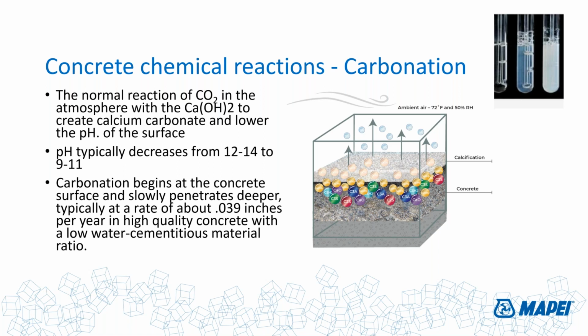So that's helpful for us as floor covering installers, to allow a concrete slab to carbonate, and there is a considerable difference in solubility in water. Calcium carbonate is not that soluble in water. Calcium hydroxide is extremely soluble in water. I would rather be working on something that is not soluble when I'm putting water-based adhesive on top of it, rather than something that is extremely soluble. That carbonation process typically will decrease the pH of a concrete slab, which is sometimes up to 14, down to a livable range of 9 to 11 in terms of pH.